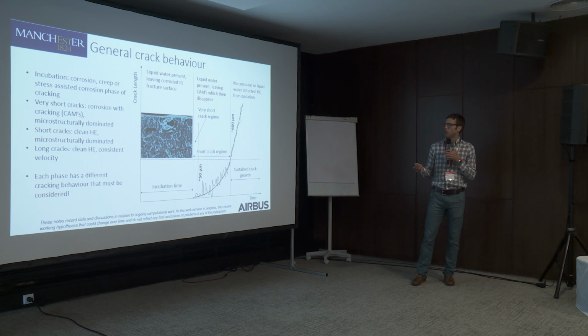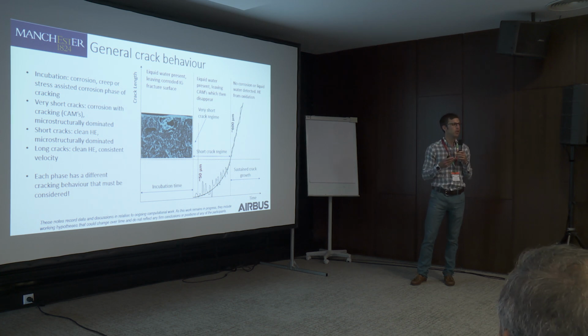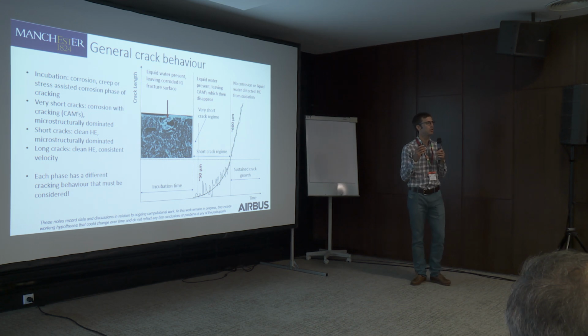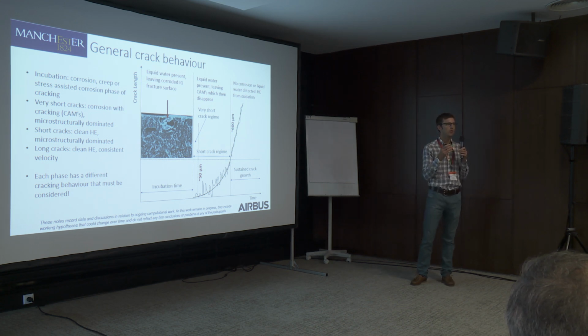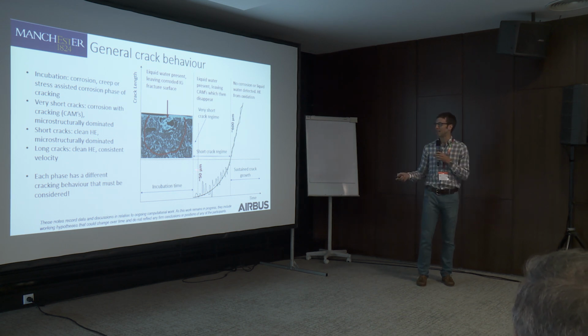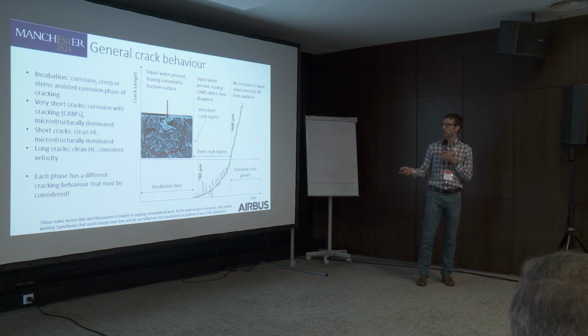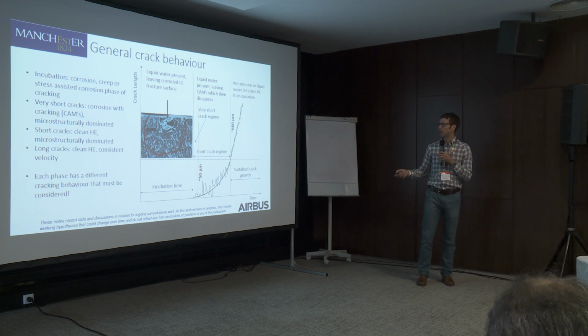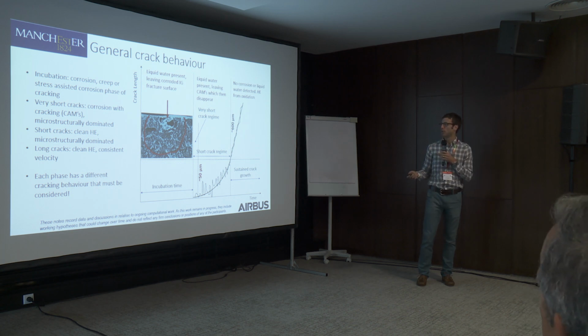So in summary of what we found putting together the crack observations and the fractography of the samples, we see that we get an incubation time where we don't see any visible changes, but what we know from the post-mortem evaluation is that we've got corrosive attack, albeit at an extremely small scale, less than 5 microns, just quite gentle oxidation, followed by something that we've had to add in here, which is this behavior in the short crack regime where we do see crack arrest markings, which later disappear. We observe these crack arrest markings up to about 50 microns, but the short crack regime that we've defined based on the mechanical behavior extends up to 600 microns. So there's maybe slightly different things happening here.